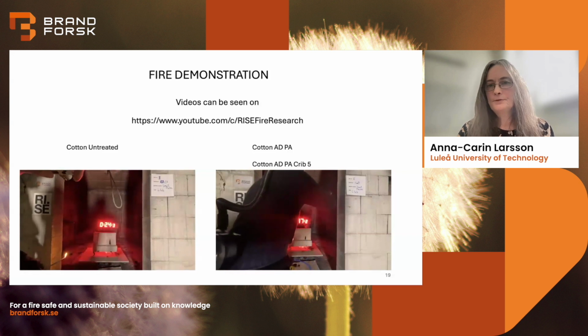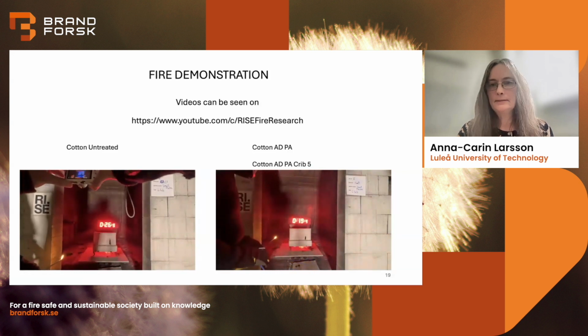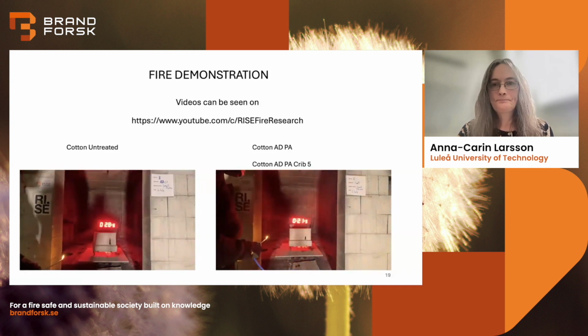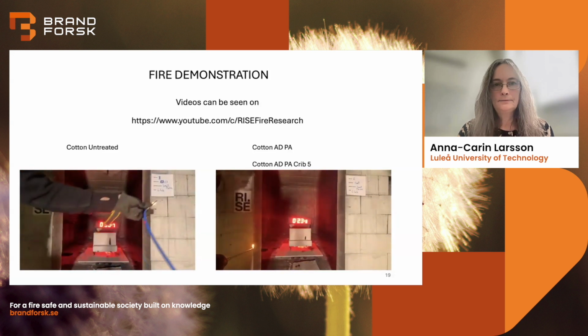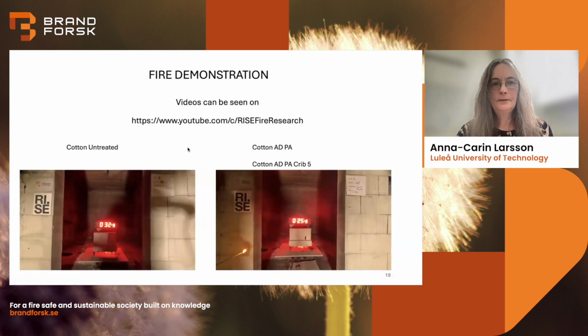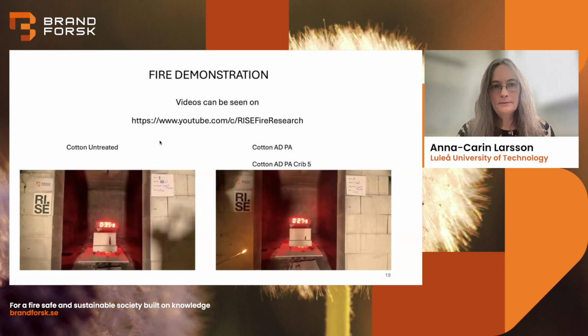The timing differs a few seconds, but you will still see a difference. See that the untreated cotton here to the left is starting to burn and the fire is spreading, while the treated cotton still only has a small black spot.